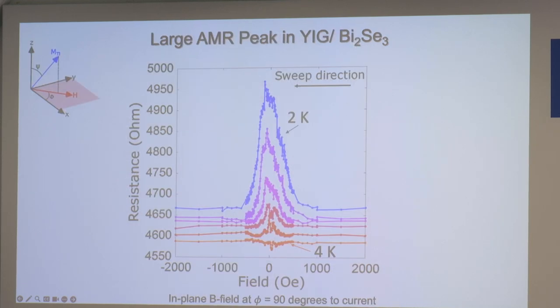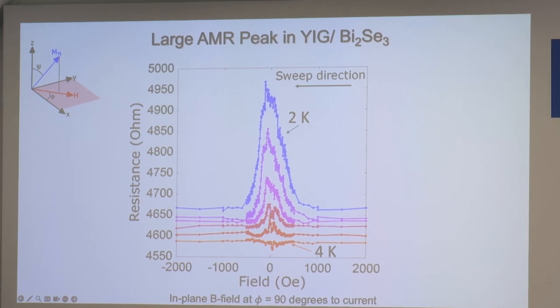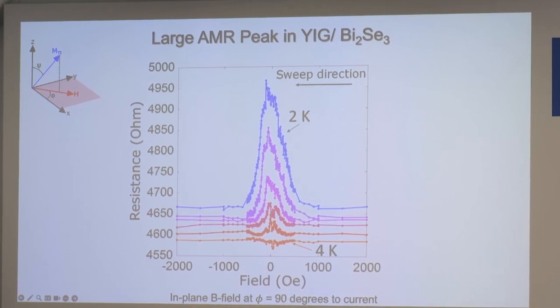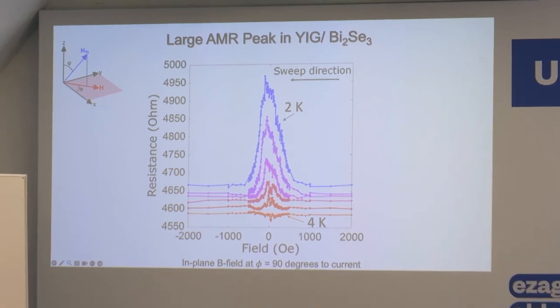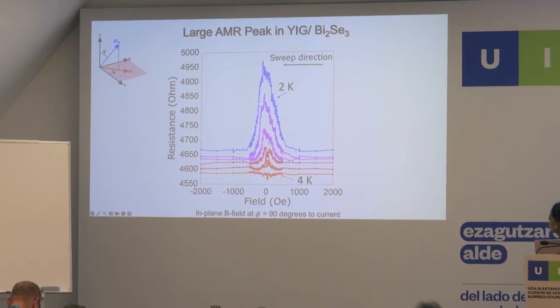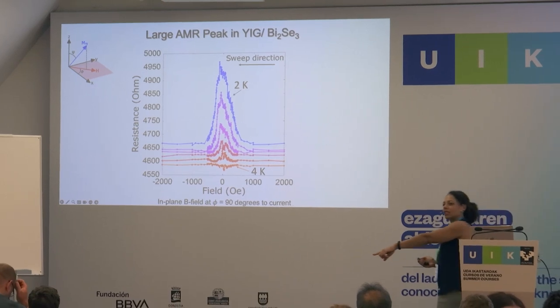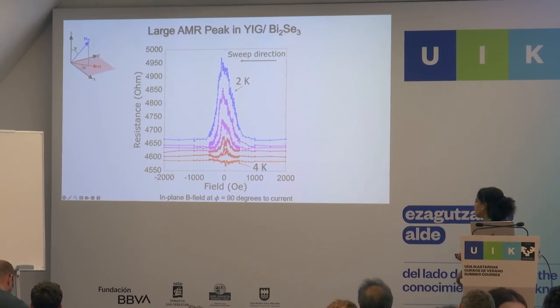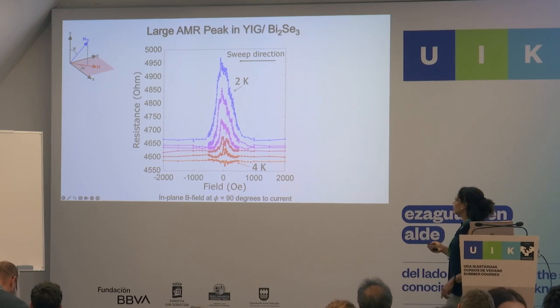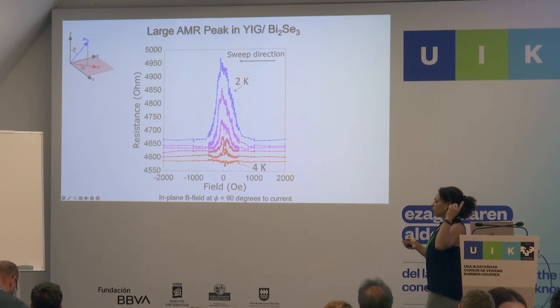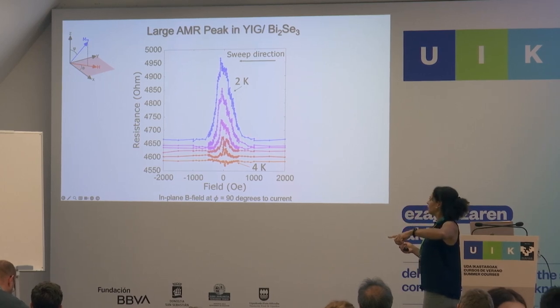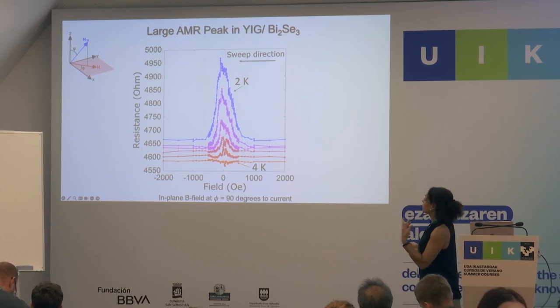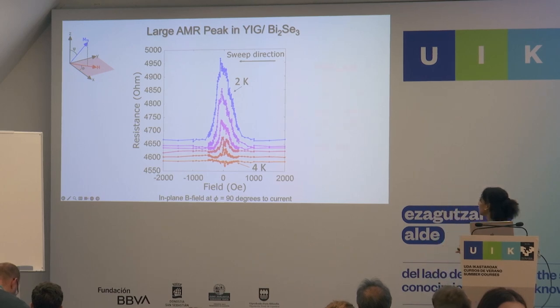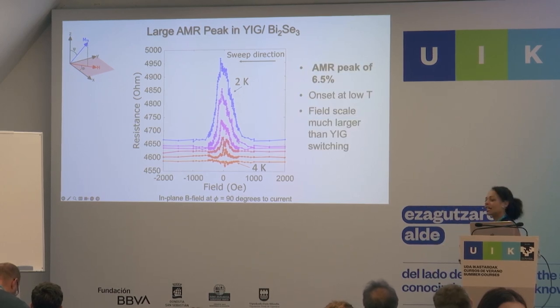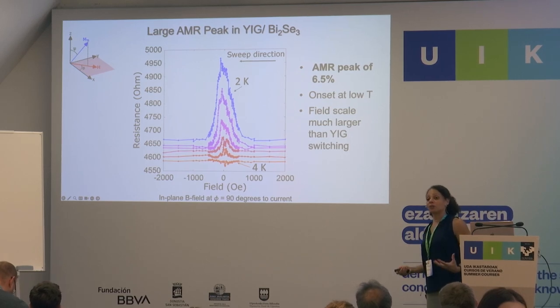Okay, and this is the data that we saw in this case. So here what you're seeing is a function of it's a YIG bismuth selenide bilayer where we apply a strong in-plane field. And so what we expect to see is the magnetization, as you start with a gap at zero field, so you should have high resistance. And then as we apply the in-plane field, we rotate out of plane until we get a low resistance. And so this was really nice, but we also want to note that what we see here is a really large peak. A 6.5% peak is much bigger than what's been seen before.